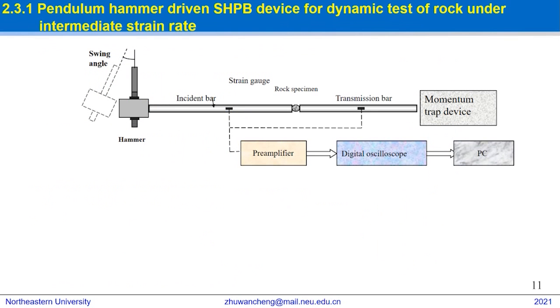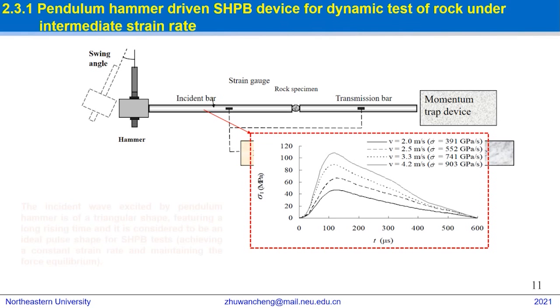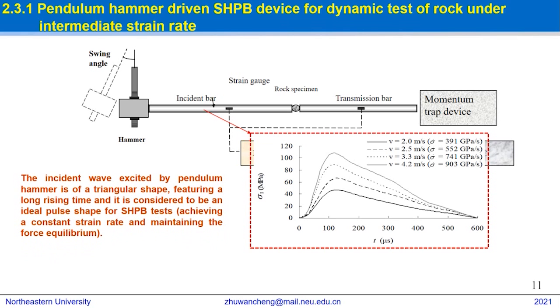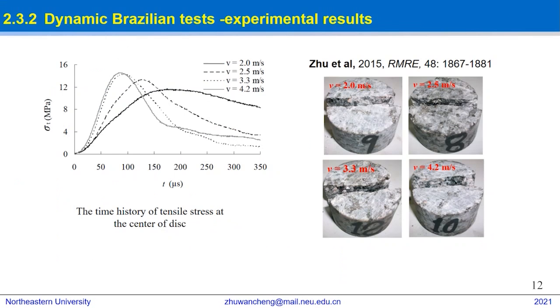This slide shows the pendulum hammer-driven SHPB device for dynamic test of rock under intermediate strain rate. The incident wave excited by the pendulum hammer is of a triangular shape, featuring a long rising time, and it is considered to be an ideal pulse shape for SHPB tests, achieving a constant strain rate and maintaining the force equilibrium. The figure on the left shows the time history of tensile stress sigma t at the center of the Brazilian disc during the SHPB test driven by the pendulum hammer.